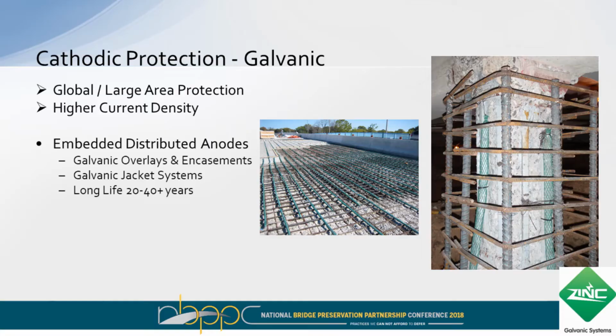If you want to go to higher level protection, moving from corrosion control more into cathodic protection, you need larger anodes. You're generally looking at larger areas of protection. And this is some deck repair and overlays where you see these green strips are long galvanic anodes. They're placed in the repair area, and then in some areas were cut into slots where you had sound concrete. Then the concrete was placed back, and then you had a membrane and asphalt placed on top. Based on the amount of anodes placed there, you're achieving full cathodic protection of the deck. And these can be designed for longer life.